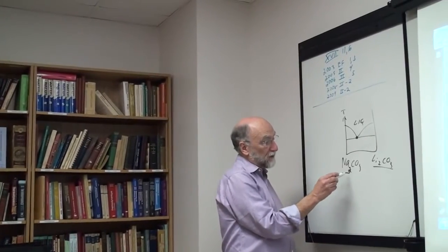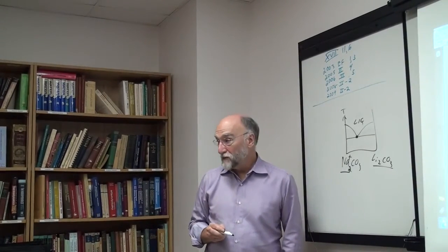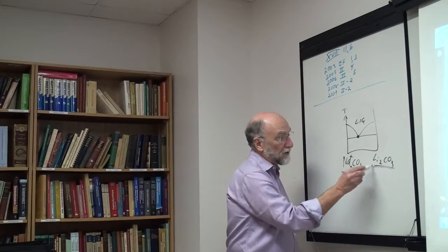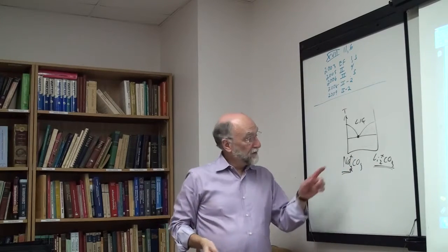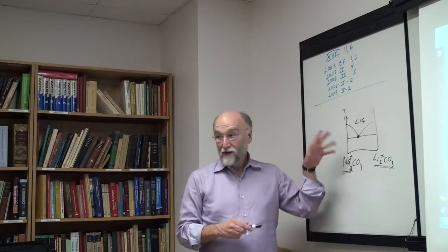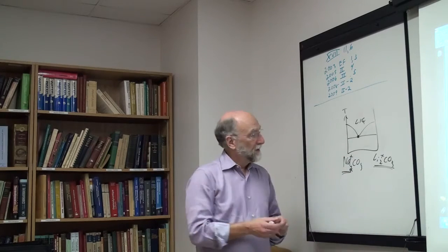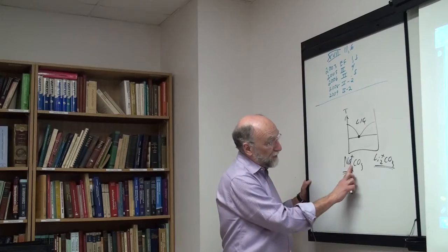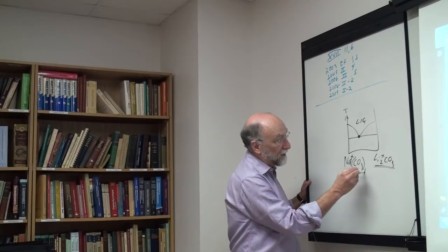The thing is, you have a mixture of sodium carbonate and lithium carbonate. But every sodium carbonate actually produces 2 sodium ions. So as we've written it here, you really have 2 moles of sodium ions mixing with 2 moles of lithium ions. So you've got twice the mixing entropy. So one way around it is, let's redefine the components as sodium carbonate 1/2,